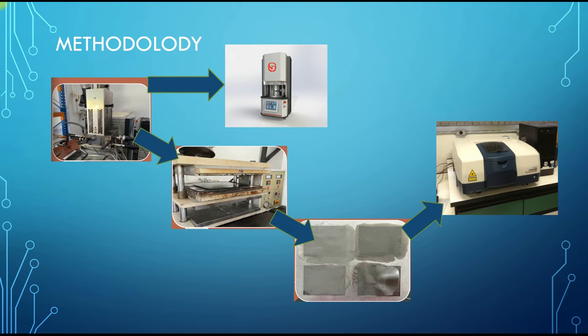Some of the compounded specimen is then hot pressed at 150 degrees Celsius with 150 kilogram force. After that, when we got the samples, we went to FTIR to support our analysis.